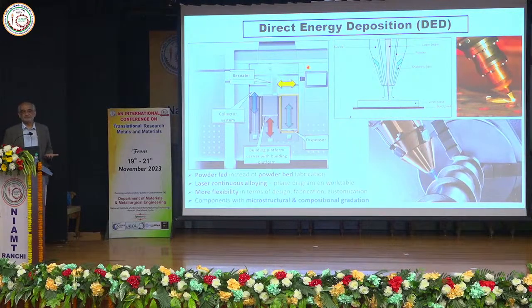But on the other hand, if you have the attitude of exploring something new, we should try something different. In that case, you might like to change the composition, you might like to change the dimension, you might like to also vary along the time you are actually feeding the powder. So there I'll have a different configuration. Instead of a tank of powder, I'll have a nozzle, which essentially is a coaxial nozzle. So through this central region, I'll have the laser beam coming through, either fed through some reflection method or directly by a fiber. And I'll have these nozzles which are feeding the powders directly into the spot.